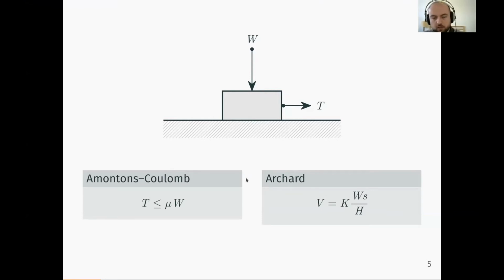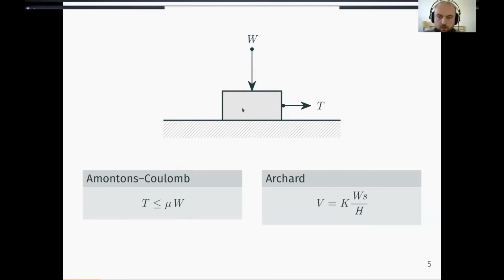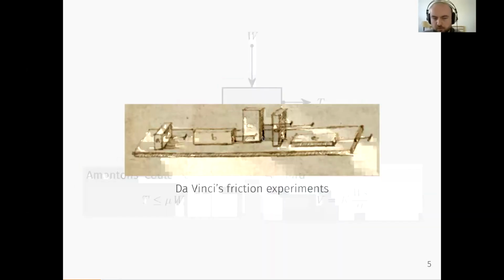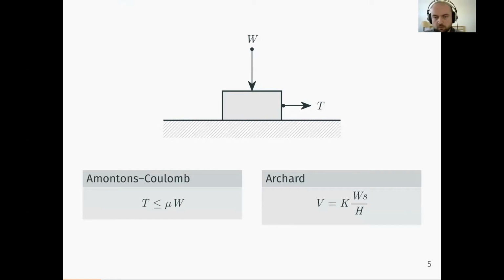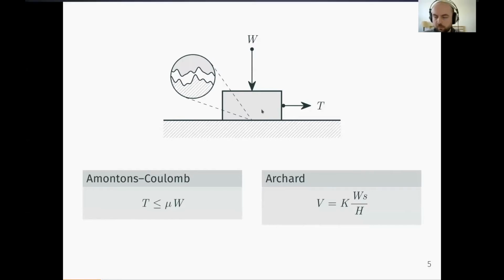What they also have in common is a linear dependency on the normal force and an absence of dependency on the apparent contact area. Here, in both of those equations, the size of the apparent contact does not play a role. We've known this for a few centuries now, because Da Vinci actually did experiments on this, where he was measuring the static friction force for different orientations of a single block, and he found that the orientation of the block had no bearing on the static friction force. Now, the reason this is the case is due to inevitable roughness that occurs at the interface. And roughness is a fundamental aspect of tribology, and it governs a lot of what we observe at the macro scale for friction and wear.